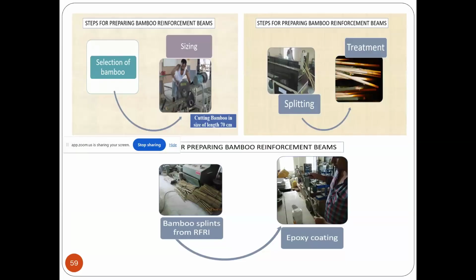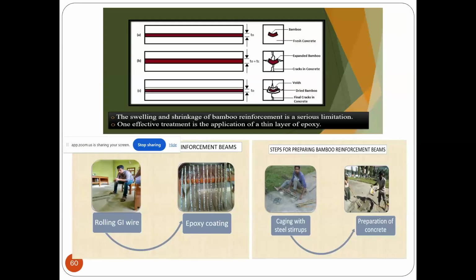Then the other one is the poor interfacial bonding. For poor interfacial bonding, the bamboo was rolled with GI wire. There was another study. The bamboo splints, which were epoxy coated, were rolled by different kinds of wires, by GI wires, then by coir and other threads also. And there were pull out tests, and finally it was found that epoxy coating with GI wire gives the best bonding.